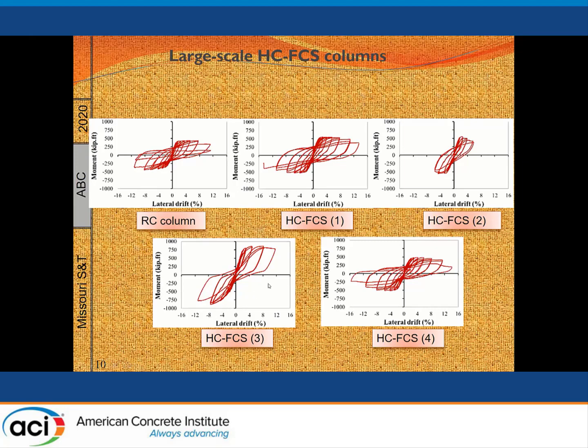And then the one on the bottom left, we did not provide enough development length. So you have an embedment issue. And this is why we have pinching and slippage in the hysteretic loop. And then the fourth one, we have a higher steel thickness. So we see a little bit higher strength.